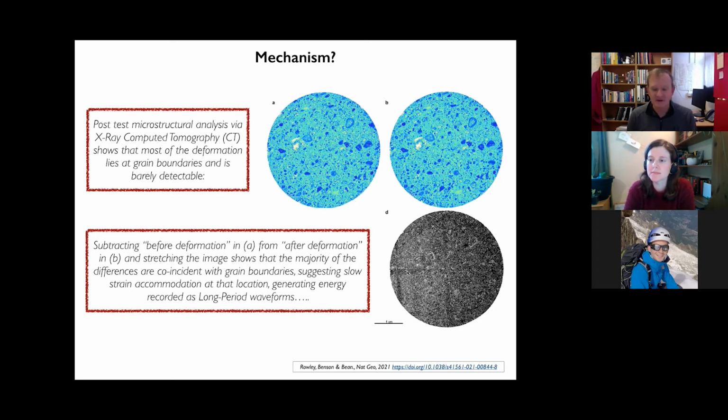I don't have a slide, I'm afraid, to demonstrate this, but he proposed a very simple scaling relationship where the size of the fracture generates lower frequency data, and this ratio between fracture length, let's say, keep it simple, fracture length divided by the frequency that you measure, has a certain ratio, about 10 to the 6, let's say.